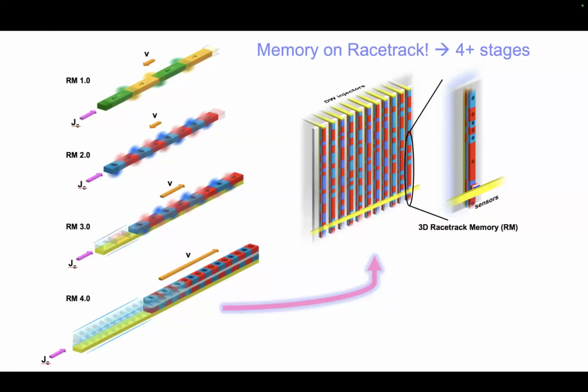In fact, it's impossible to build spin valves without eliminating the stray fields from the two magnetic layers in the spin valve sandwich or in the magnetic tunnel junction. Similarly, you have to eliminate the stray fields. In all cases, the solution is a synthetic antiferromagnet, which is something I invented in 1991 and was used in the very first spin valve devices. The synthetic antiferromagnet is very simple, as shown in this cartoon in racetrack 4.0. In this case, we build on top of the racetrack a second identical racetrack coupled through a thin metallic layer that gives rise to something called the Ruderman-Kittel interaction.